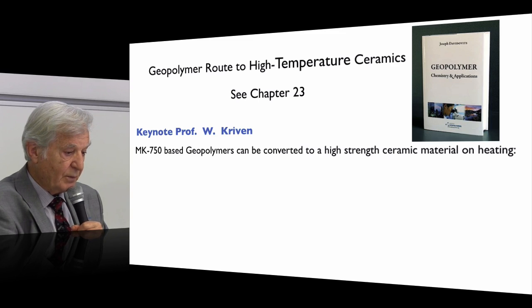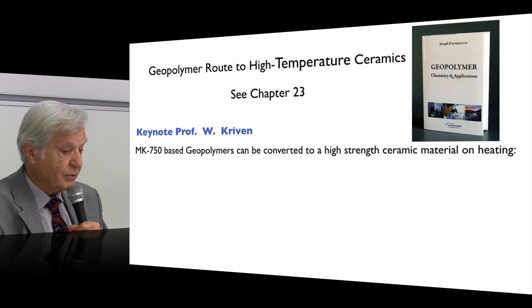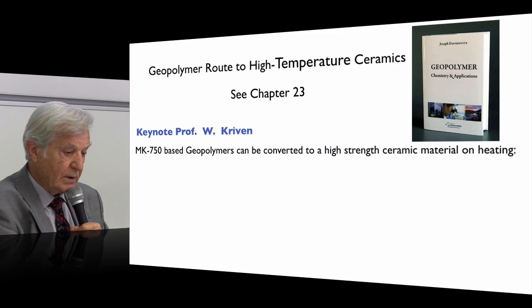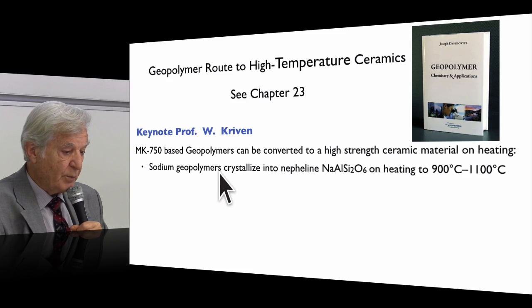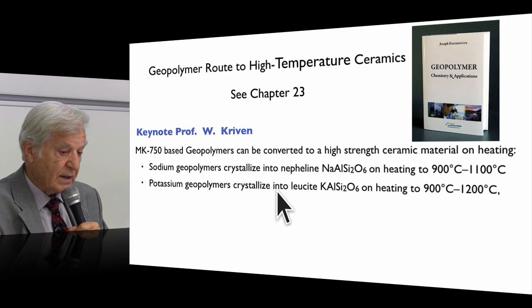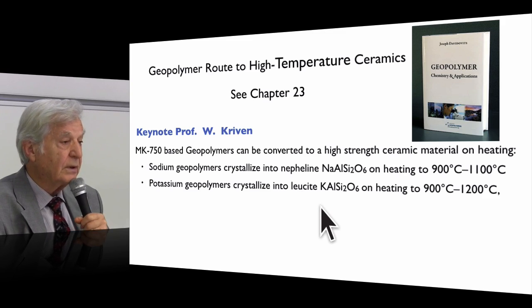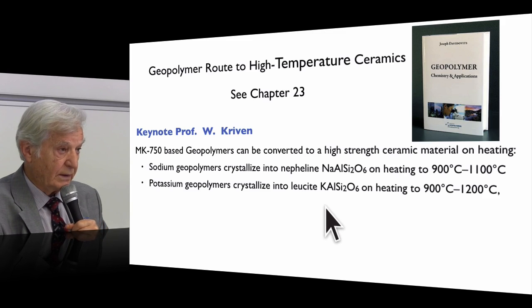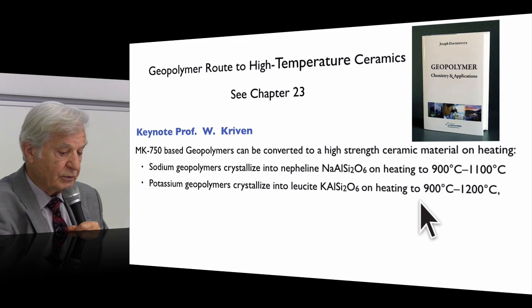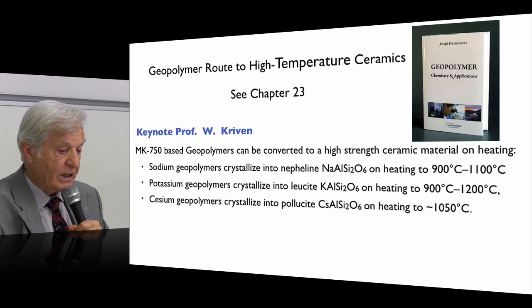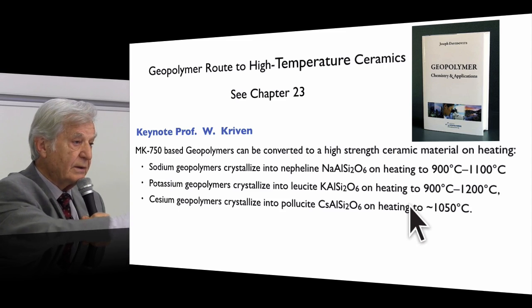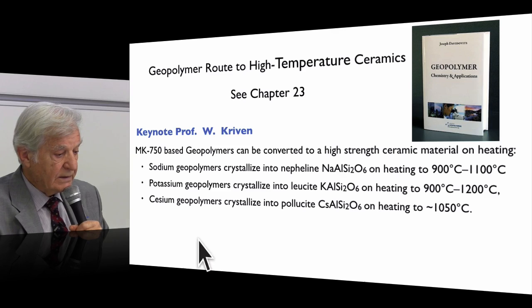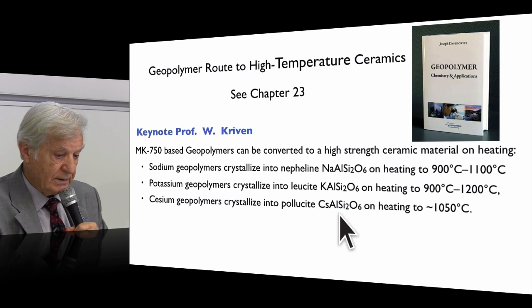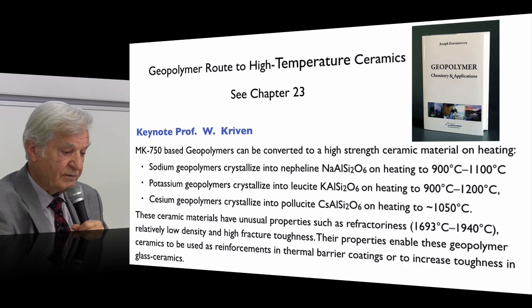She and her teams have developed metakaolin-based geopolymers that can be converted to high-strength ceramic materials on heating. We have sodium geopolymers that crystallize into nepheline on heating to 900 and 1100 degrees C. Potassium geopolymers crystallize into leucite. These are very well-known ceramic materials, on heating to 900 to 1200 degrees C. They are formed at low temperature, and then they continue and crystallize. Cesium geopolymer crystallizes into pollucite on heating at around 1050.